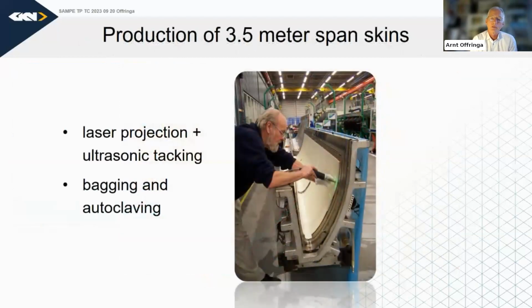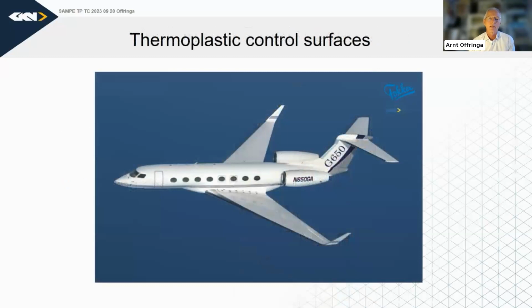We see here the layup process, laser-assisted projection, then it's vacuum bagged and then autoclaved in a fairly efficient autoclave cycle. It's faster than with thermosets, but still it is time intensive, very energy intensive, and you have bagging materials which you cannot reuse afterwards. This was in the late 90s.